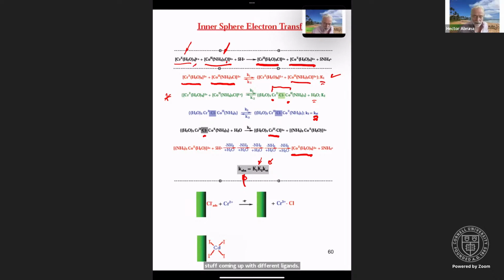The critical distinction here is that the transition state in an inner sphere process involves a bridge between reaction partners. Whether the coordination environment changes in the end is not necessary, but it's often the case, because you're talking about generating substitutionally labile species by the simple event of the electron transfer itself.